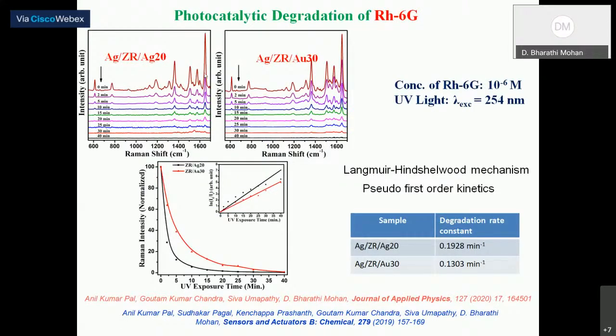And you can see here, for the different times of degradation, we have recorded the Raman spectra on both silver-based and gold-based nanostructure. As you increase the time, you can see that after 40 minutes, the Raman modes of the rhodamine 6G have completely disappeared. And it is again the same in case of gold-based nanostructure.